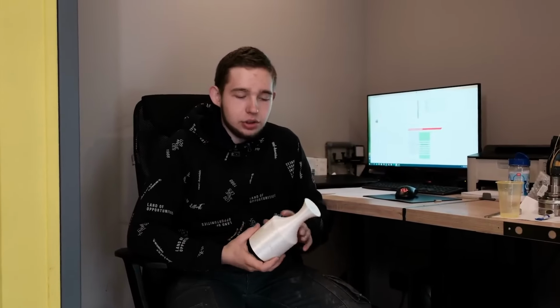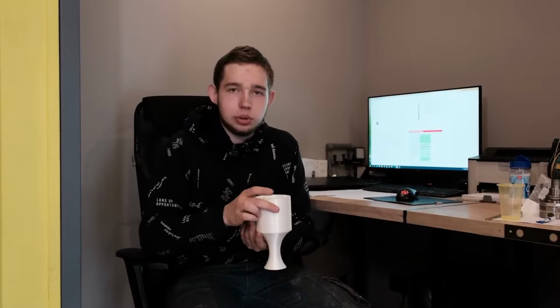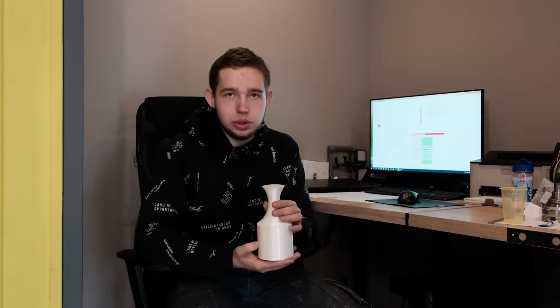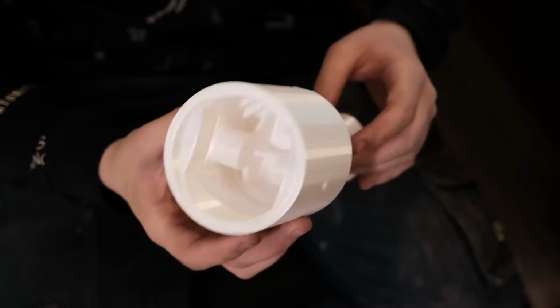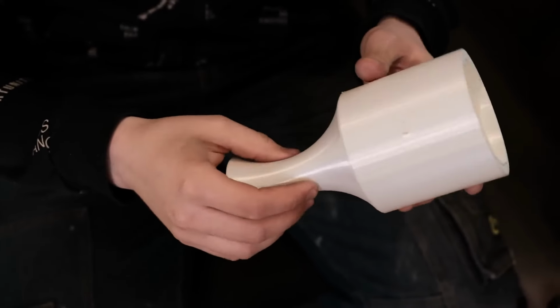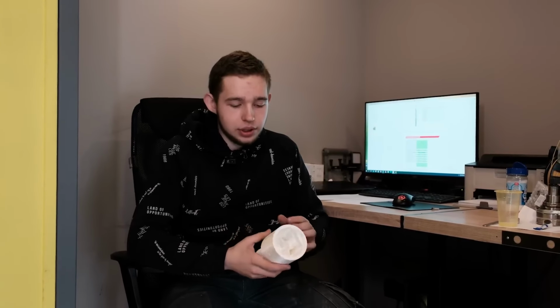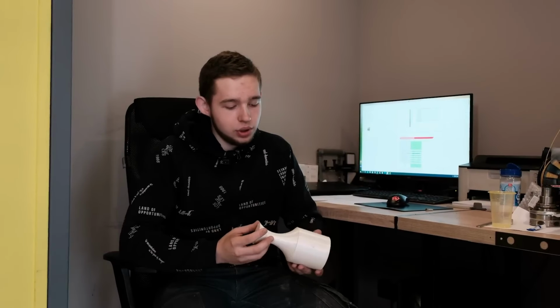So we've printed our model out of PLA plastic and attached the sprue here because this part needs to be printed in this orientation and this one in that orientation. And now we're applying our ceramic shell from a slurry with a binder, sprinkling everything with filler for about 5 to 8 layers, and we'll end up with a ceramic shell mold.